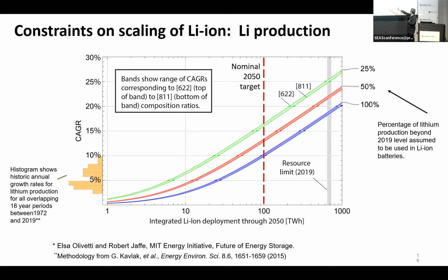If you're going to reach 100 terawatt hours by the year 2050, this is what the compound annual growth rate has to be. And what you see is that in the case where all of the lithium that you mine goes towards batteries and there's no other consumption, you need to have, well, 10%. And you might say, okay, maybe we could do that. But keep in mind that this means you have to have 10% a year, every year for the next 28 years. So that indicates how heavy a lift it is. The resource limit is over here.